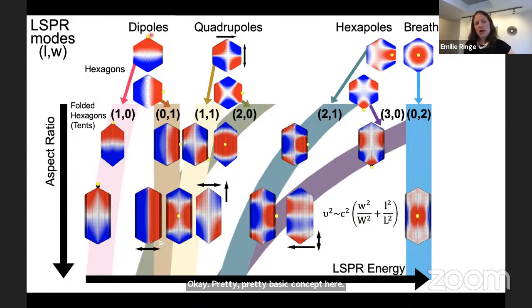As we move from hexagon to longer folded particles such as tents - the behavior is essentially the same for the other shapes - we basically break our dipoles, and then they shift in energy. We break our quadrupoles, and our hexapoles actually turn into different modes as well. Then the relative energy of these different modes cross over as the particle size increases.